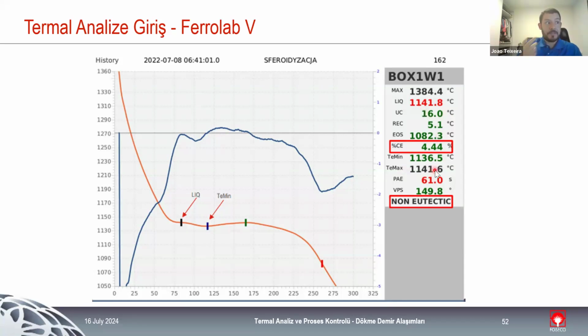We have 1136.5 degrees. So we are above the metastable temperature. So we have a 16 degrees undercooling. It's a difference between a theoretical minimum and the reference point. If the undercooling is smaller, it means that the inoculation step was more powerful. So we have a better inoculation step.